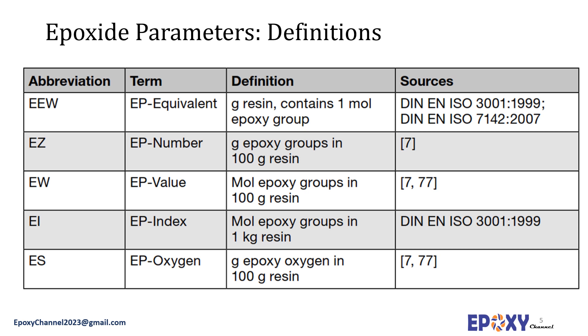The most important parameter for epoxy resin is the content of epoxy groups, because they are reactive and react with the cross-linking agent, determining the amount of cross-linking agent needed. There are different ways to present this parameter. The most common one is the epoxide equivalent weight, or EEW, also called epoxide equivalent. The definition of EEW is the grams of resin which contain one mole of epoxy groups, and it can be calculated based on different standards.